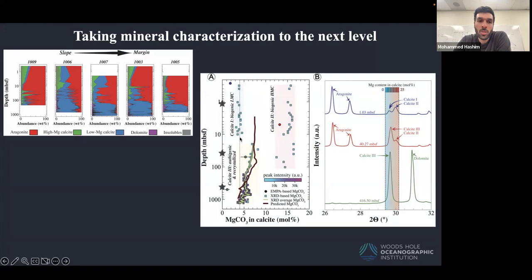So we were able to see 3 groups of calcite that have different magnesium content. And based on their magnesium contents, we were able to interpret their origin. So we have this biogenic low magnesium calcite. We have high magnesium calcite that is also biogenic.